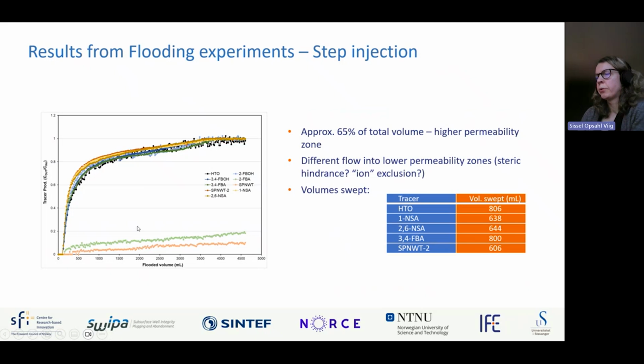And if you look further into the curves, what type of information can we gain about the system that it has been flowing through? Well, we see that we have this steep increase in tracer concentration at the beginning before it continues to increase, but with a much slower increase until it reaches a stable level here. And to interpret this, we can say that for this level where we have this steep curve, we probably have a high permeable channel. And here, this slow increase in tracer concentration shows that we also have some low permeability zones where the tracer moves through.